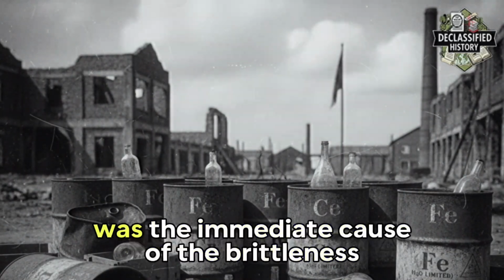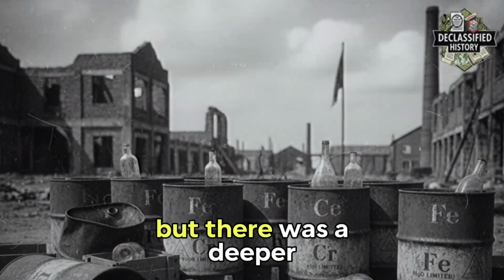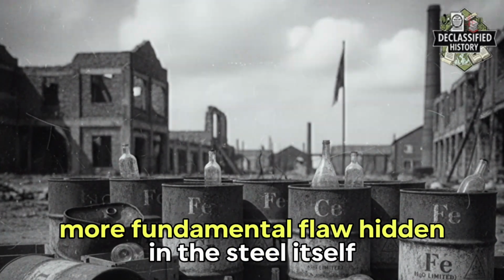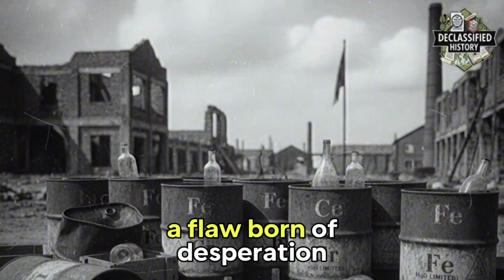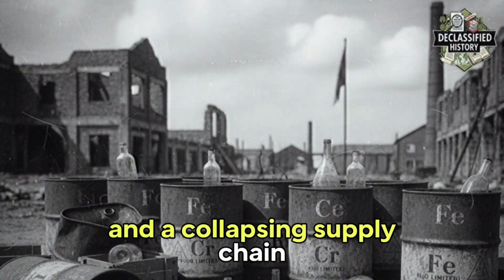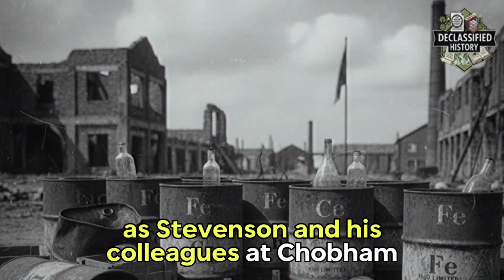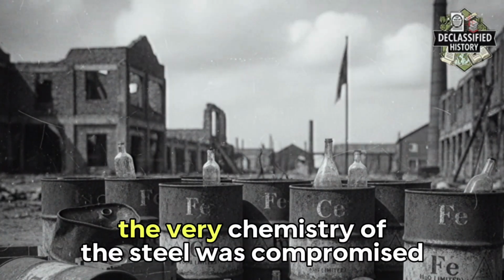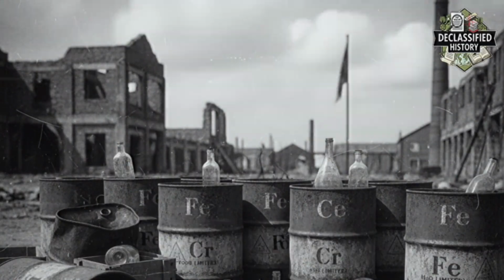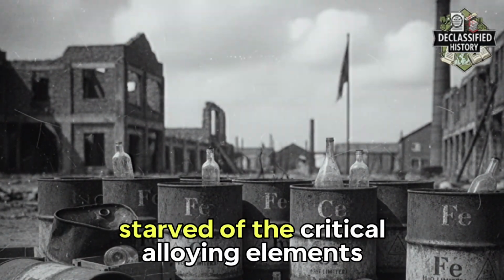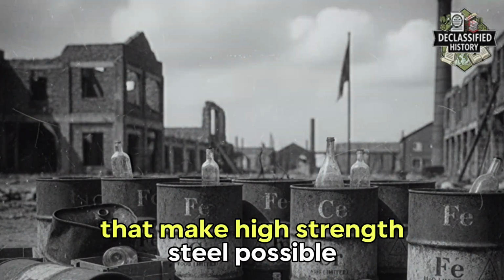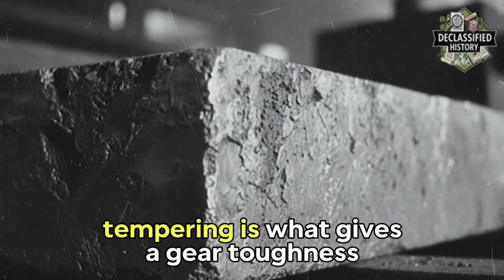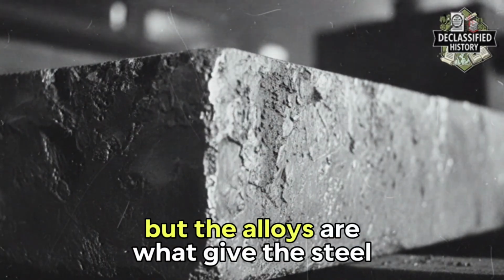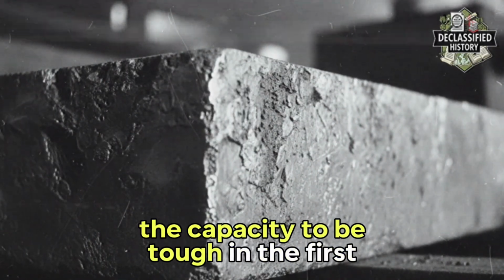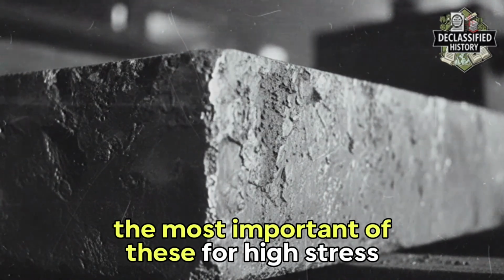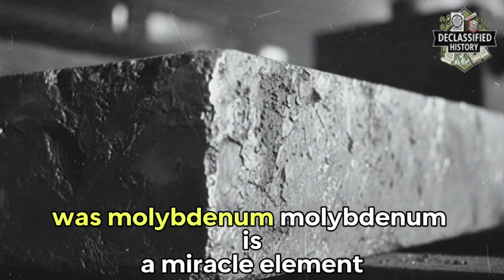The skipped tempering was the immediate cause of the brittleness, but there was a deeper, more fundamental flaw hidden in the steel itself, a flaw born of desperation and a collapsing supply chain. As Stevenson and his colleagues at Chobham would soon discover, the very chemistry of the steel was compromised. German industry was being starved of the critical alloying elements that make high-strength steel possible. Tempering is what gives a gear toughness, but the alloys are what give the steel the capacity to be tough in the first place. The most important of these for high-stress components was molybdenum.